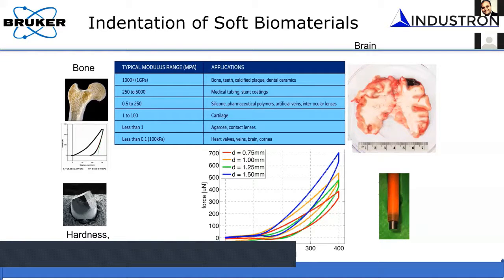I'm going to point out a few things here. The reason is that soft materials are so soft that when you bring a very sharp probe and try to make contact, you may not even sense the surface of the sample. That is the problem if you use a sharp probe, because by the time you sense some force, you are already deep into the sample, and the assumption that you have the geometry and a contact size associated with the geometry will not hold good.